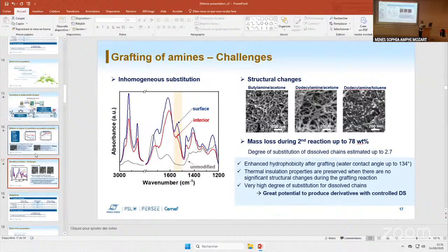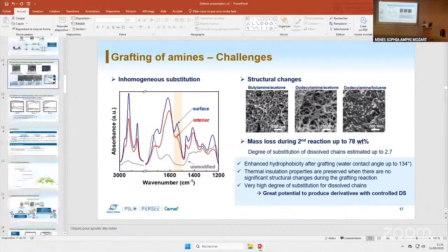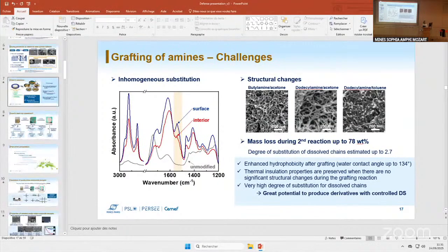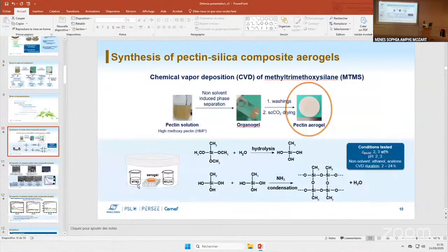I want to quickly revisit the MTMS CVD, the chemical vapor deposition. You mentioned that you tried also grafting with the monofunctional silane hexamethyldisilazane. Is that correct? Yes, correct. Do you know the work of Satoru Takeshita on chitosan, where he did also a hydrophobization of chitosan, an amine-bearing polysaccharide, with a monofunctional silane?